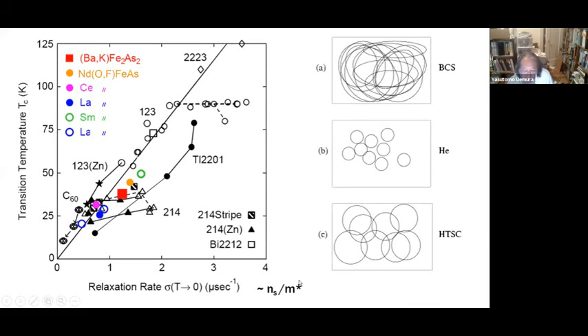But the simplest thing we can do is, now we are doing the measurement to determine n over m star. And so if you have the information of m star, you can essentially calculate how many carriers you have. And if you have the coherence length, then you can say how the spatial pairs are overlapping. And if you do so in the BCS superconductors, you have many, many pairs overlapping with each other, as you know. In the case of a typical Bose-Einstein-like condensation system, helium, you have nearly independent bosons touching barely with each other. So